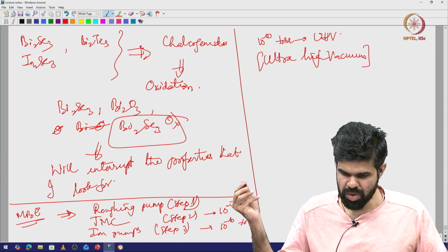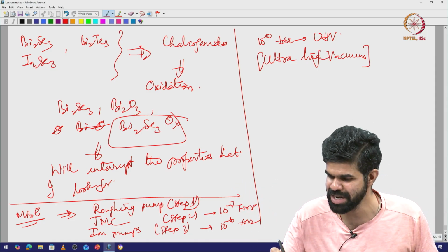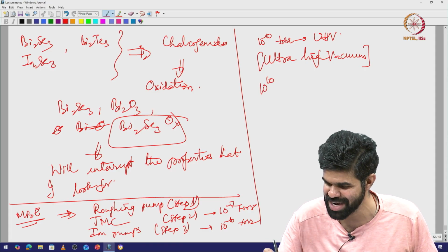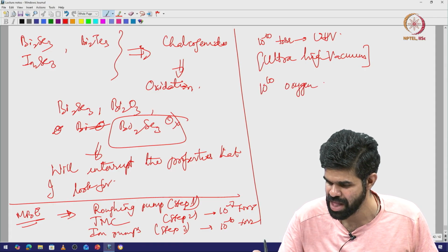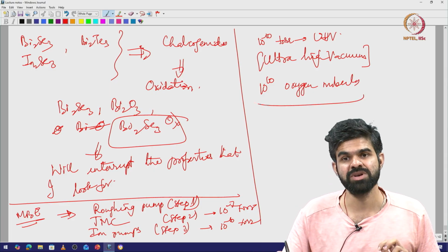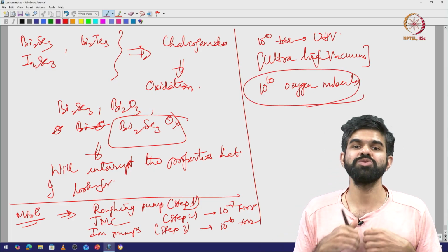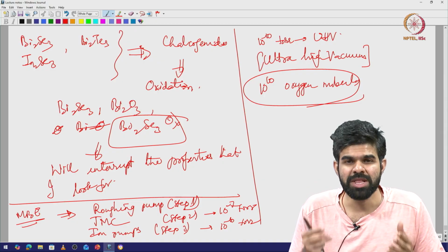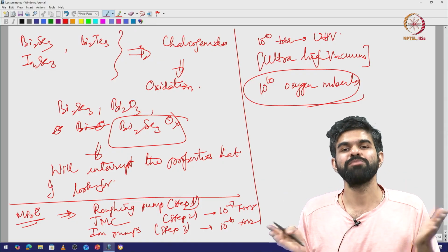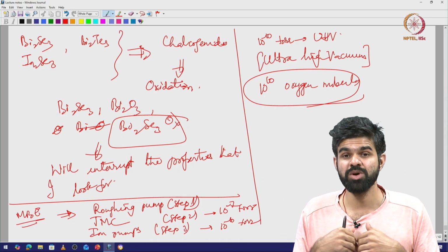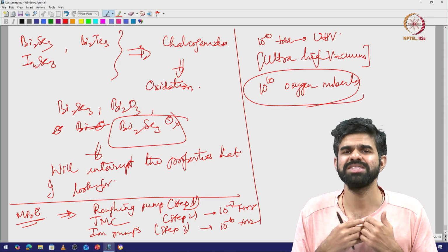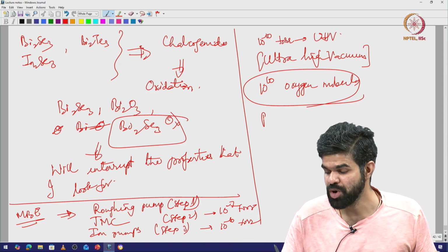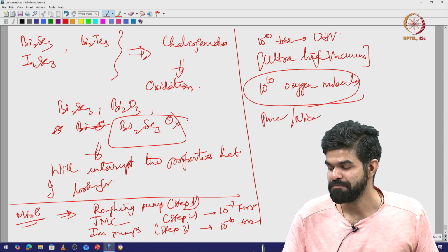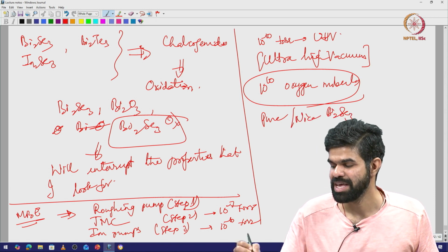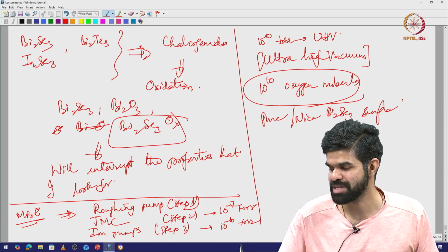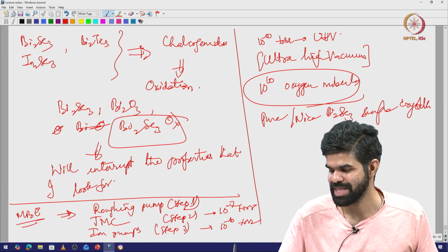If I then count the number of gas molecules there, at about 10 power minus 10 torr I have 10 power 10 oxygen molecules. It turns out that at 10 power 10 oxygen molecules, the partial pressure of oxygen is so small that the amount of oxygen that reacts with my bismuth selenide is negligible, so that I get pure, nice bismuth selenide single crystalline thin films.